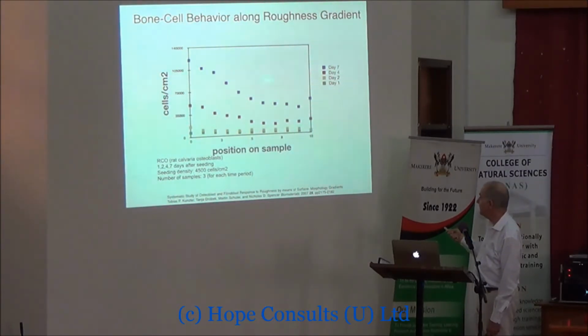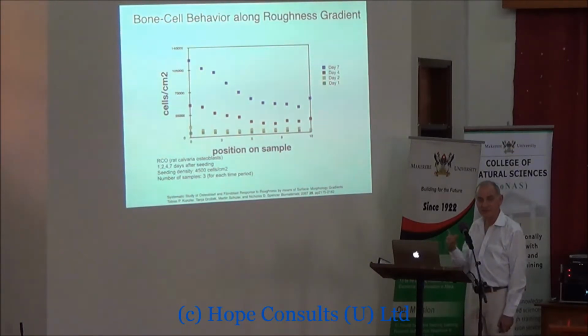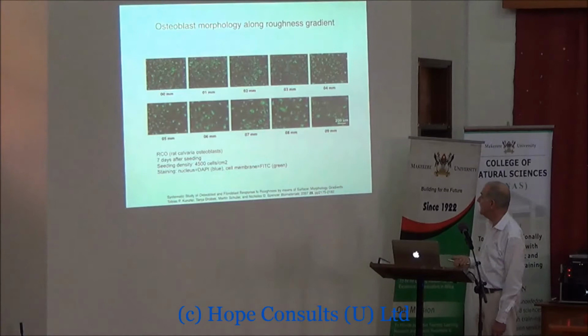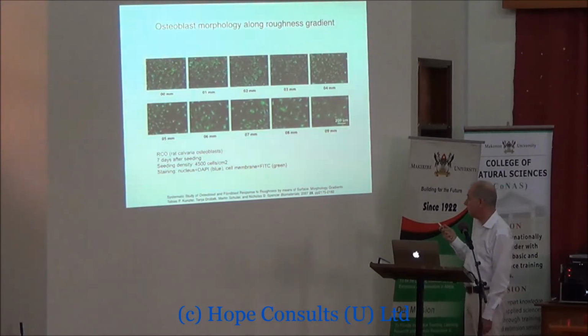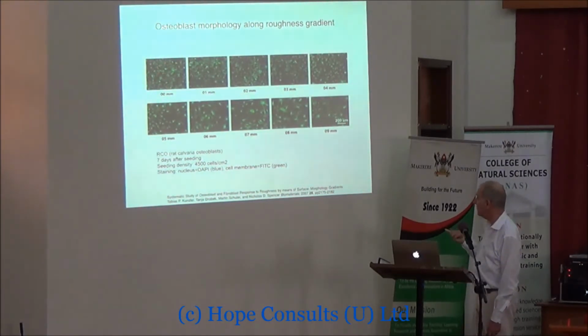So the blue color ones are after 7 days, and you can see there's an enormous difference between the rough end here and the smooth end in terms of the number of cells. So roughness has an incredible effect on the proliferation of these bone cells. And if you look in the optical microscope and you stain them, it's even more obvious.